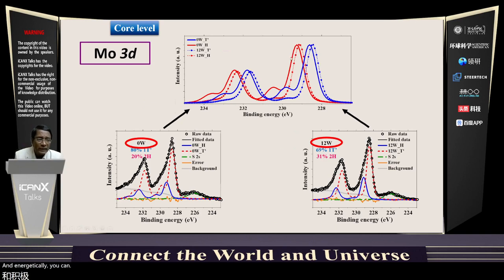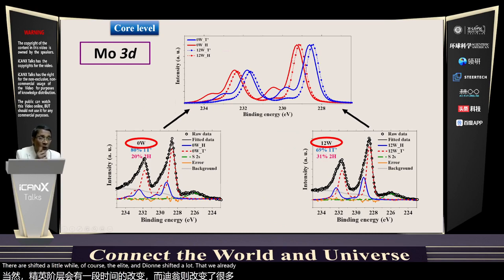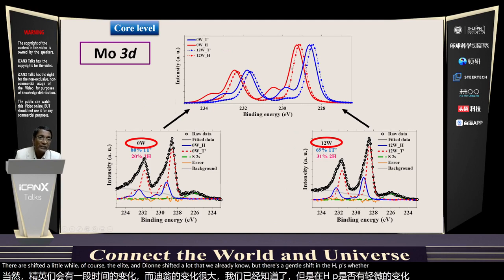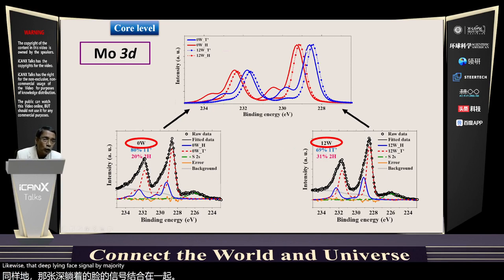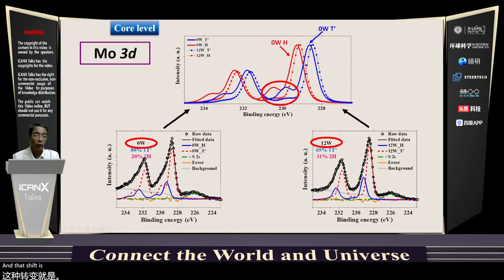And energetically, you can see that this is the zero wash H sample. This is the 12 wash H sample. They are shifted a little. Of course, the H and T are shifted a lot, that we already know. But there's a gentle shift in the H phase, whether it is in the T prime phase or in the H phase. Likewise, the T prime phase signal is also at slightly lower binding energy if it is zero wash, but when I wash it thoroughly, it shifts a little higher. Not only the shift, you can see that the plasmon is intense in the zero wash sample, but it is not there in this other thoroughly washed sample. And this shift is in the order of 0.3 electron volt.